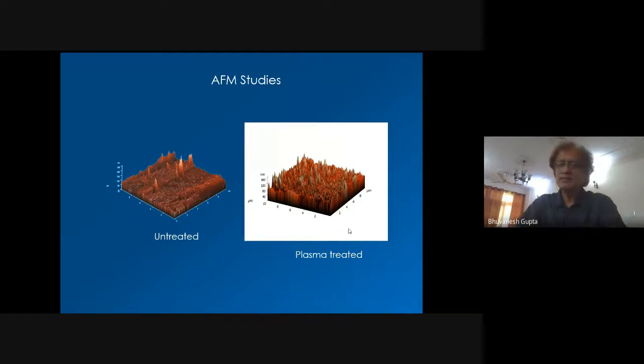So what you see is that in plasma processing, the surface becomes non-homogeneous, surface etching is there, but suddenly you achieve something, but you might lose something else. And the surface becoming like that is not a problem. This is, in fact, in the nano range. Okay, it's not even micron. The nano-scale change on the surface is there, which is not a problem for medical applications. Next.